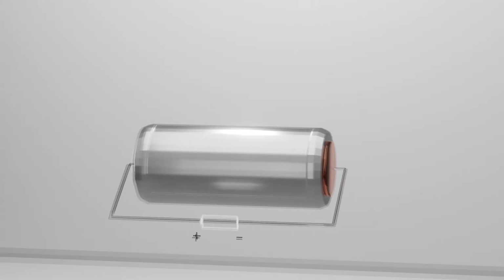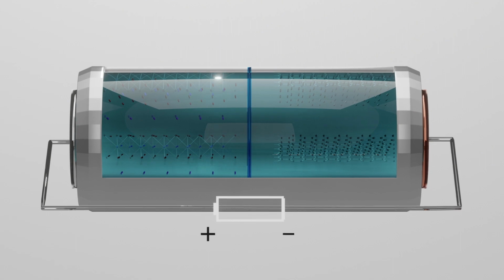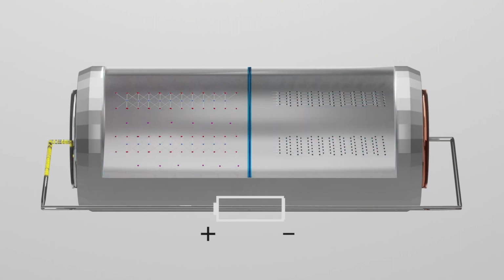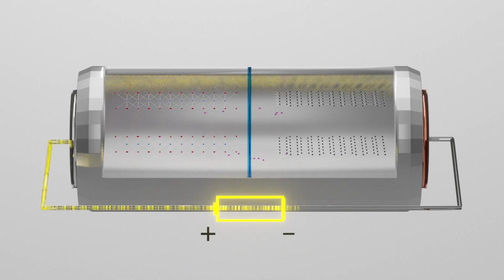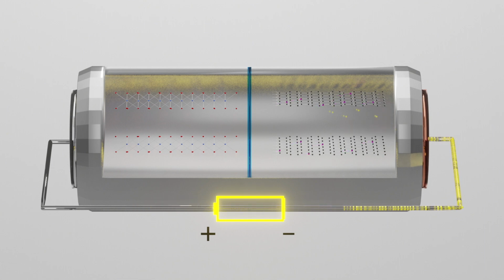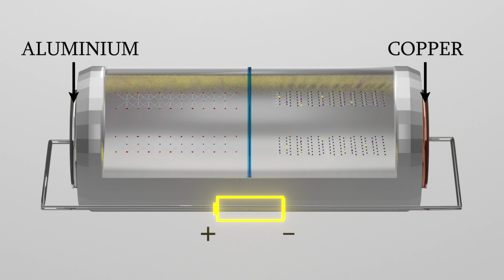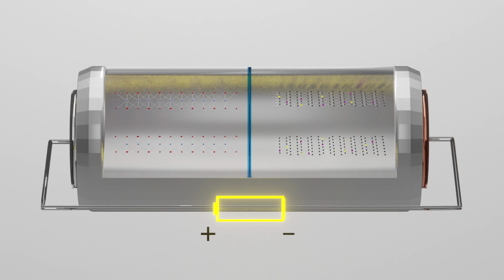When charging, the cell is connected to a power source, and so in the cathode, the lithium's outer electrons will be attracted to the positive side of the power source, and are readily lost from the lithium due to its high oxidation potential. The electrons then flow through the circuit to the anode through current collectors, made from aluminium for the cathode and copper for the anode, each to avoid unwanted reactions. Meanwhile, the lithium ions from the cathode de-intercalate and migrate to the anode in order to balance the charge from oxidation by dissolving into the electrolyte.